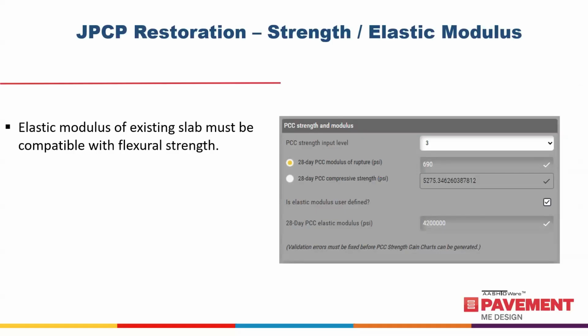Now, the elastic modulus of the existing slab must be compatible with flexural strength. And what that really means is the relationship between modulus and flexural strength should be kind of in lockstep along the maturity curve that you would normally see for both properties. The problem is if you have the flexural strength that is too high in terms of the elastic modulus, then your fatigue cracking could go to almost nothing.